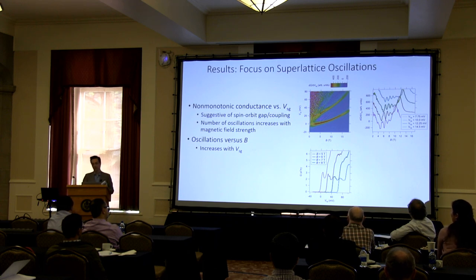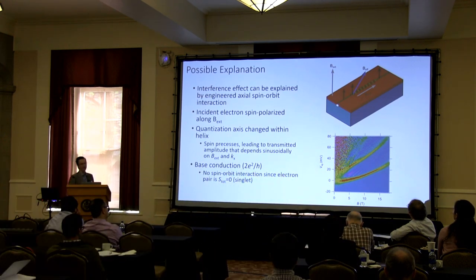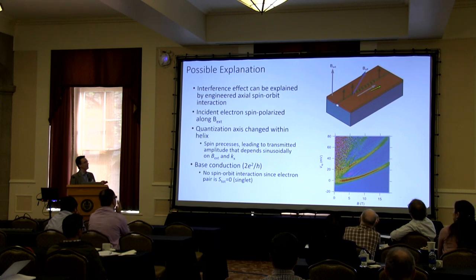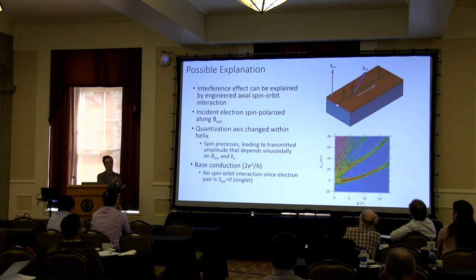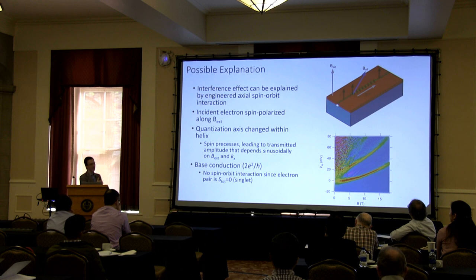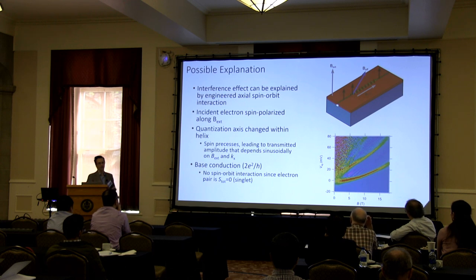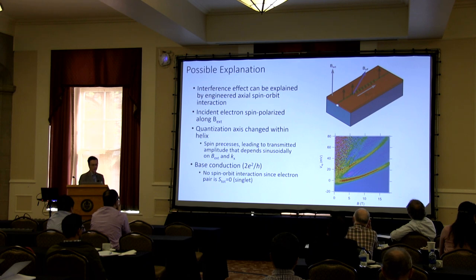that has been engineered through this process. And so the picture that we have, the sort of working model right now, is that we have a magnetic field in the z direction. And then when the electrons enter the spiral wire, the effective quantization axis is changed. So there's now a longitudinal component due to the spin orbit effective magnetic field, and the electrons precess about this new axis, and depending on whether they complete a full precession cycle or not, they would either have a full transmission or a partial reflection. And we see this in these characteristic signatures of an engineered 1D spin orbit interaction.